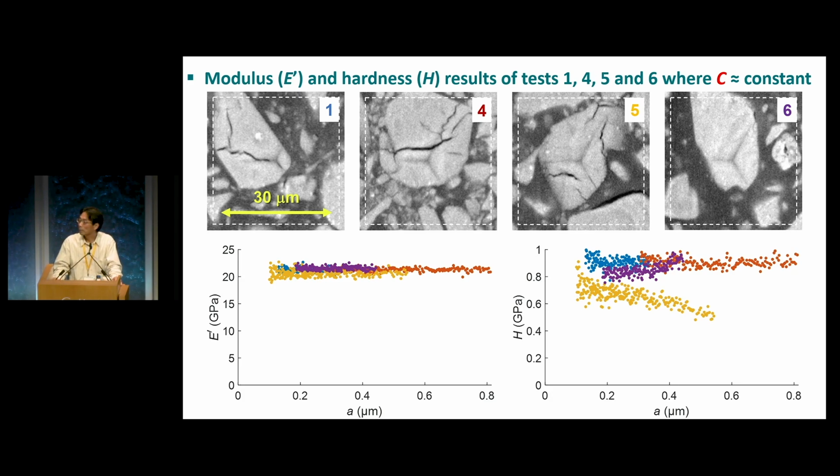And some of the motivation of this work was that when we were trying to compare properties of the materials at different scales, we found that at the macro scale, or this meso, DMA scale, the properties of materials were governed mostly by the binder, whereas in the indentation we found a very different situation. We started to think whether it is actually possible to characterize components of the material, which could be useful information for, for example, modeling of the behavior or generally understanding the historic materials.